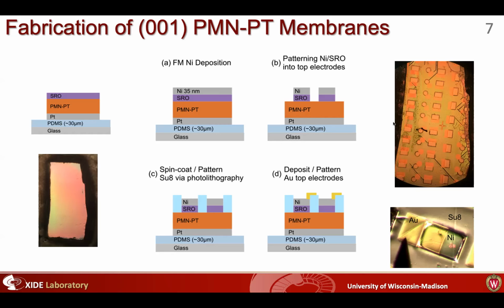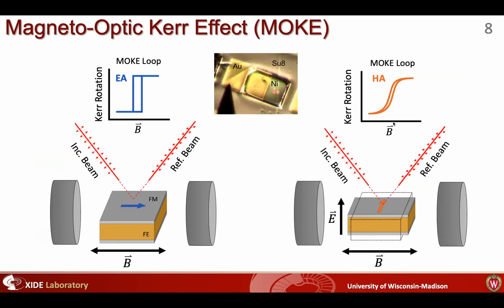So a lot of the challenges were on the fabrication side, but we do this offset gold electrode so that now I can come in with my electrical probe and still leave the nickel kind of free from the probe so that I can measure the magnetic anisotropy. So just briefly, how we did that was we would use the magneto-optic Kerr effect. Just like many other magnetic measurements, you're sweeping a magnetic field and monitoring a hysteresis loop. So if your anisotropy is parallel to the magnetic field, you get an easy axis square loop.